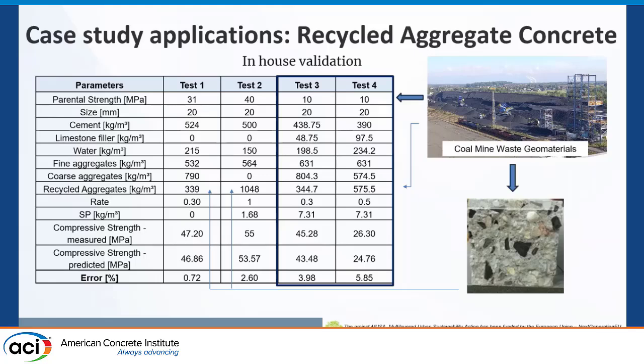So this concrete here contains recycled aggregates coming from a concrete which already contains recycled aggregates. And you can recognize it from the parental strength. We were quite happy because the prediction of the strength that we got matched quite well the results of the experiments that we did. Actually, these materials here were already in the neural network, these were new.